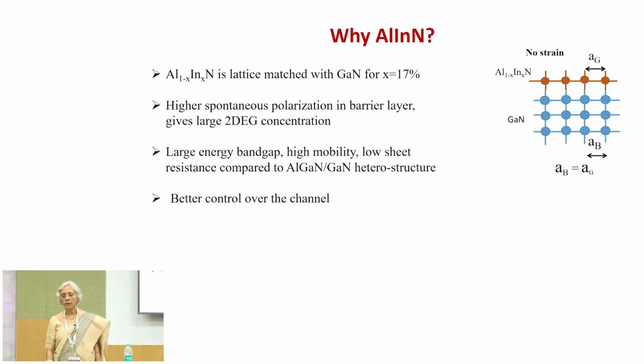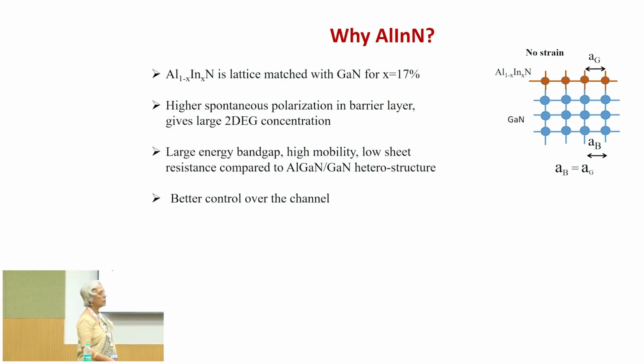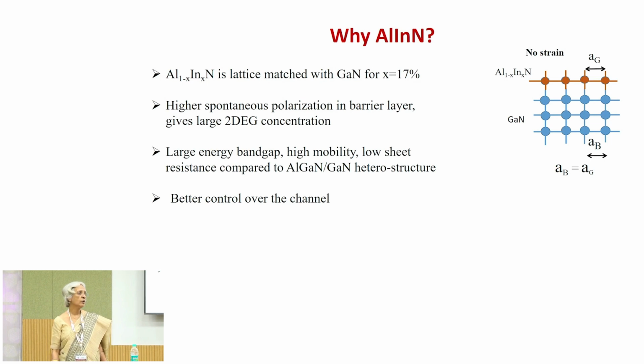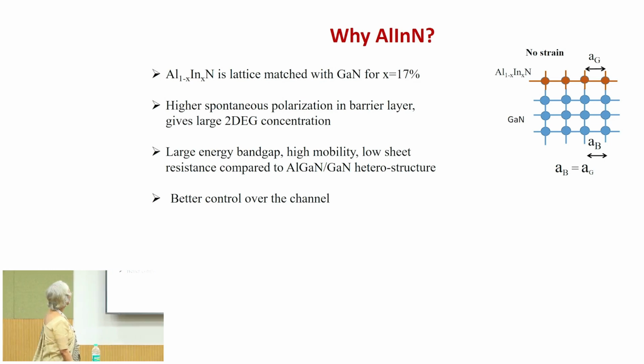As you know, one problem in the AlGaN-GaN heterojunction is that aluminum gallium nitride is not lattice matched to gallium nitride. As a result, there is a lot of inbuilt strain in the aluminum gallium nitride layer, and these are all piezoelectric materials. So, when we apply voltage during operation, further stress develops in the barrier material, which leads to a lot of defect generation and eventual malfunctioning of the device. So, in order to make these devices reliable, we felt that aluminum indium nitride will be better suited because it is lattice matched to gallium nitride when we have a mole fraction of aluminum of 83%.